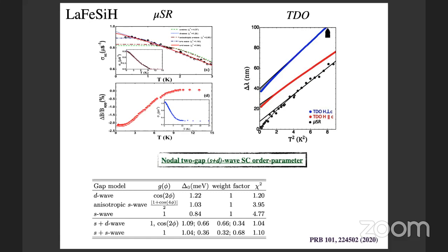Okay, so we also did the tunnel diode experiment, and we also observed the power law behavior at low temperature. This is similar to whatever we observed in the µSR experiment. So it matches with our µSR result, and we conclude that there is a presence of line nodes in the superconducting gap structure.